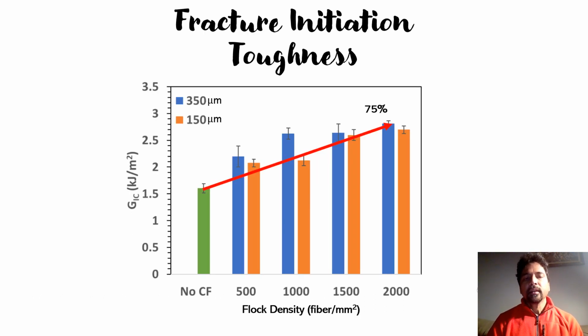Coming to results, as you can see here, with the no flocking condition, the fracture initiation toughness is around 1.5 kilojoules per meter square. However, by addition of the carbon fibers, you can see a significant improvement in the fracture initiation toughness. For a system of 2000 flock density of 350 microns carbon fiber length, we see a 75% improvement in the fracture toughness value, which is a significant improvement, where we wanted to see these multifunctional effects of adding these carbon fibers into the system.